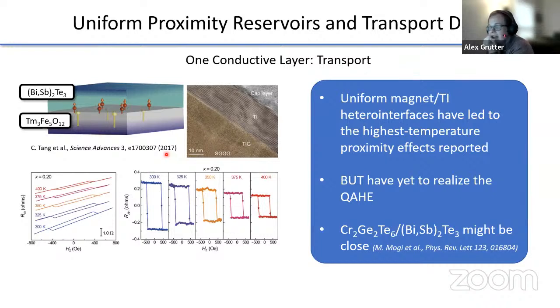In 2017. And what has been really interesting to see is that the uniform magnetic materials interfaced with topological insulators lead to the highest ordered, the highest temperature proximity effects reported. So the magnetic ordering that people report in these sorts of systems is quite high. And in fact, often you get reports that are above room temperature.